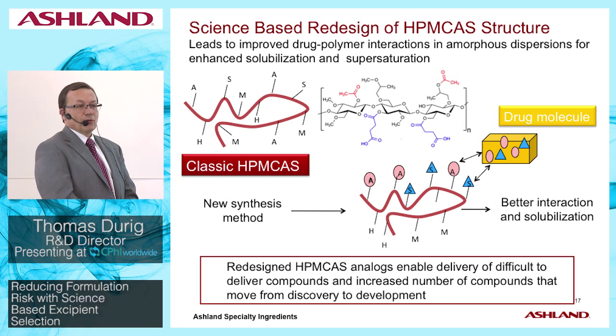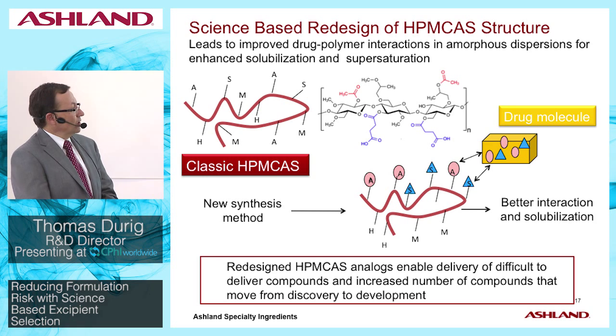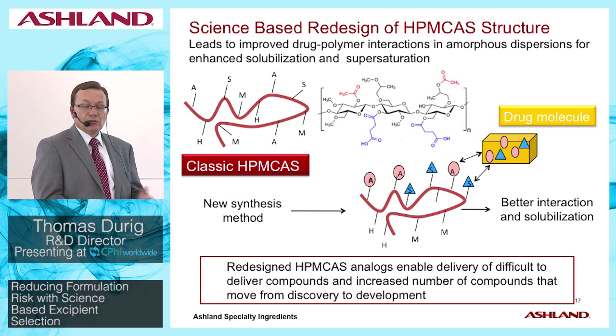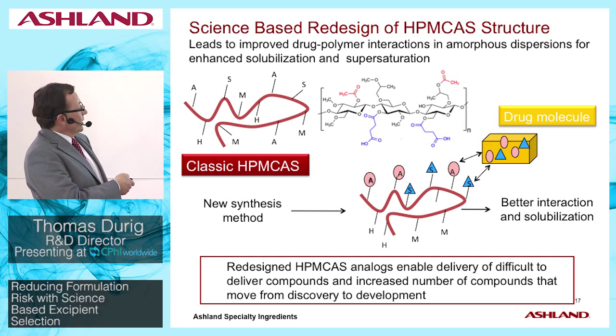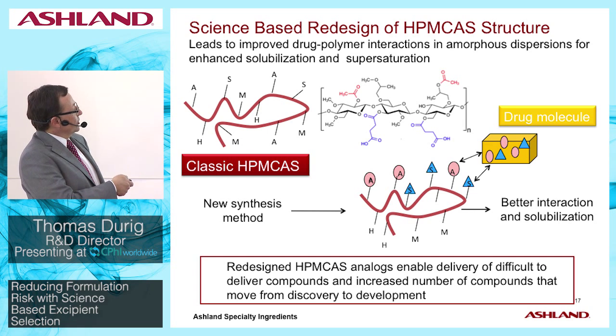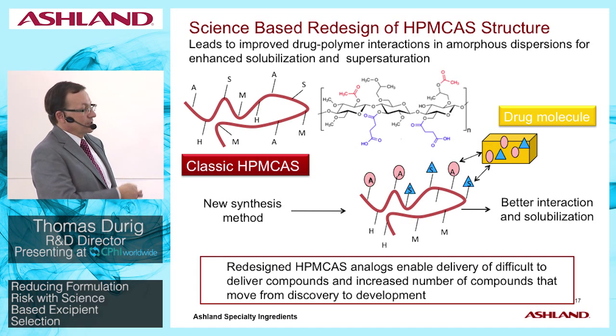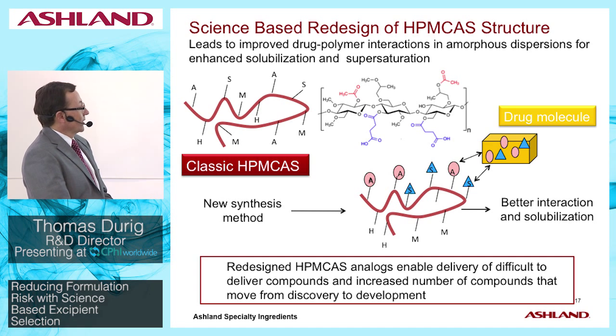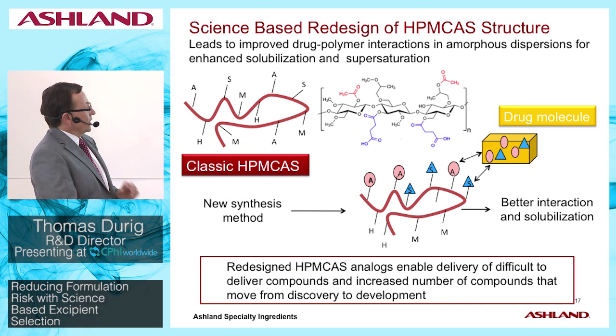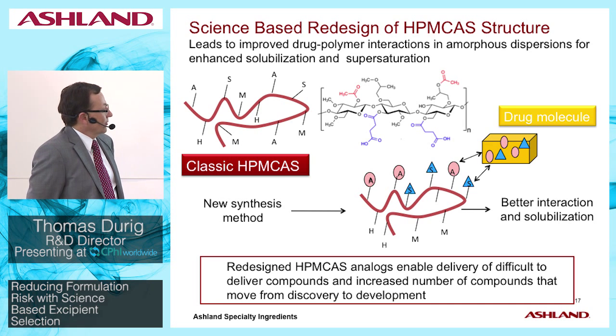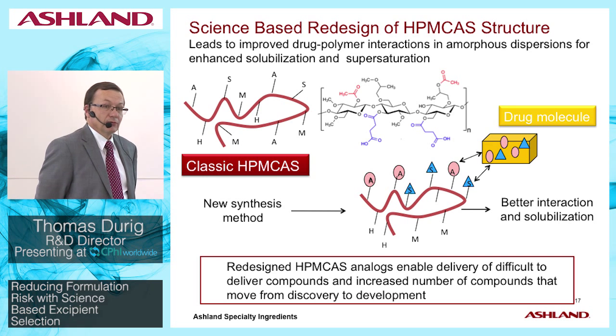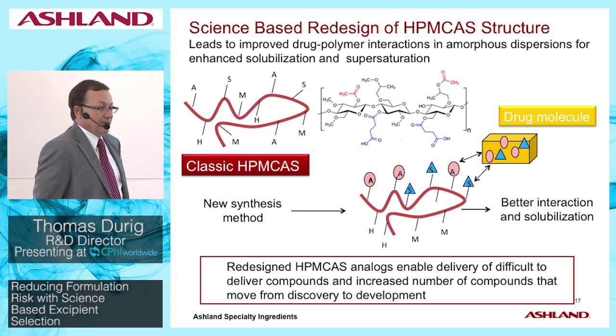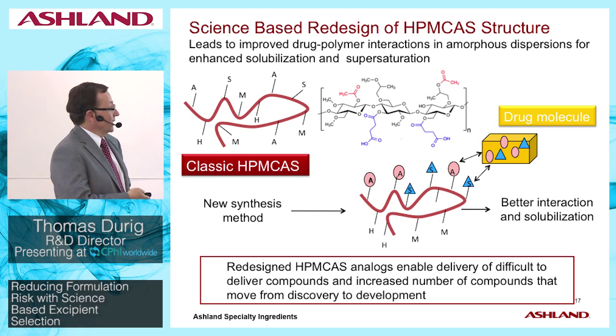And so if we look at the schematic here, this would be the classical HPMCAS, which was initially developed more for capsules and as an enteric coating, and rather accidentally found use as a solubilization polymer. And by using new synthesis methods, our scientists have found a way to rearrange these acetyl and succinyl side groups on the HPMCAS polymer to allow more efficient interaction with drug molecules. And these redesigned HPMCAS analogs are enabling the delivery of more difficult drugs, for which currently there are really not too many options to solubilize them.